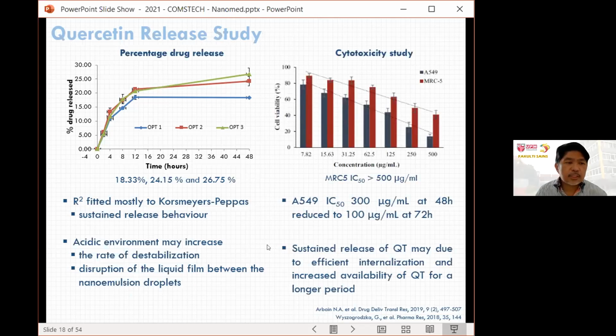And based on the IC50 data, we can see that at 48 hours it was about 300 microgram per ml, followed by a reduction to 100 at 72 hours. Again, this can be attributed to the sustained release of quercetin from the nanoemulsion, and probably due to the internalization and increased availability of quercetin for a longer period, which can be correlated with the in vitro release study that I showed here.